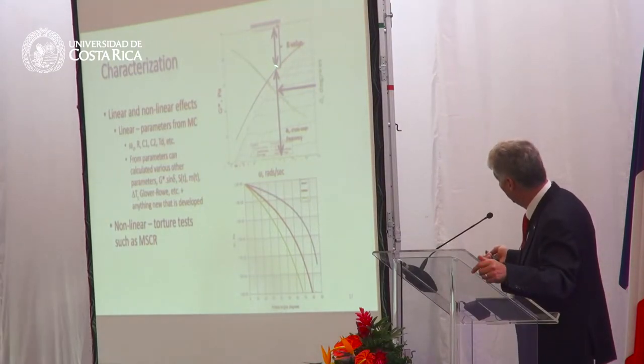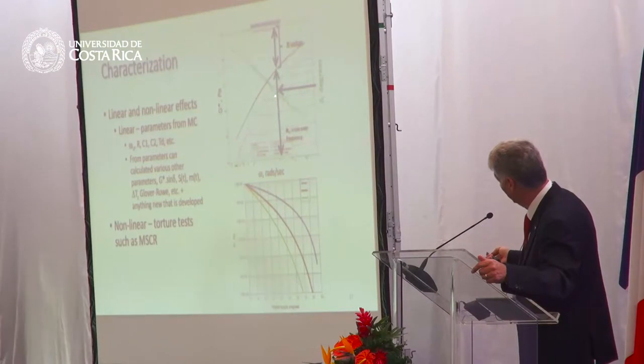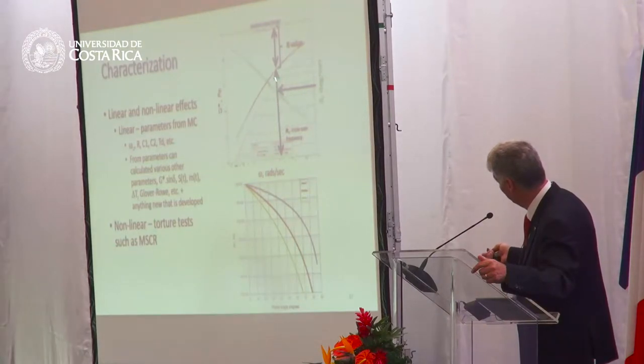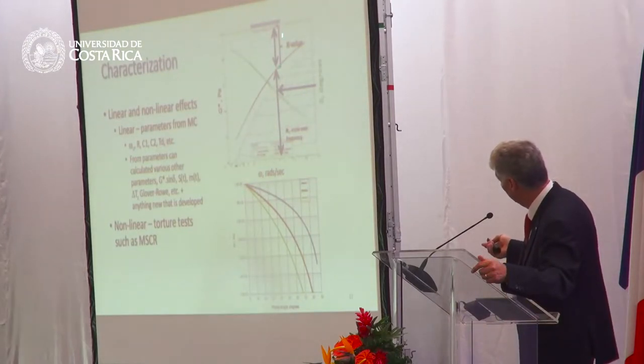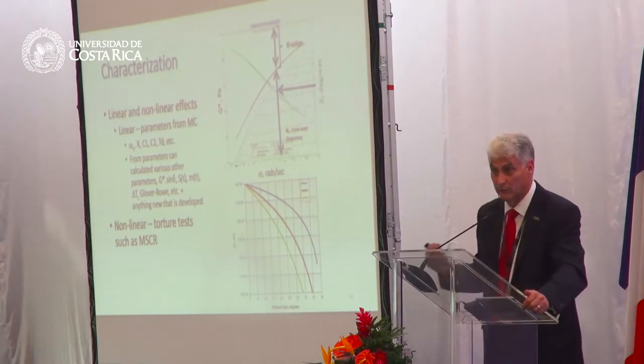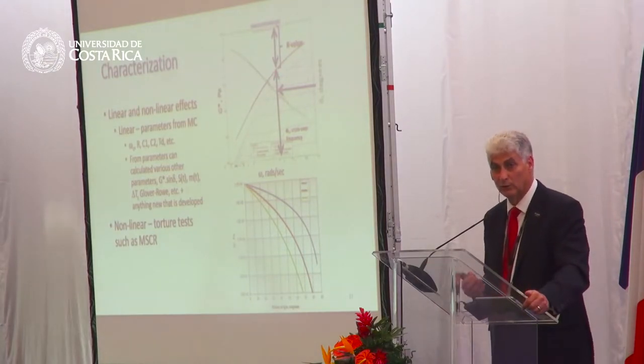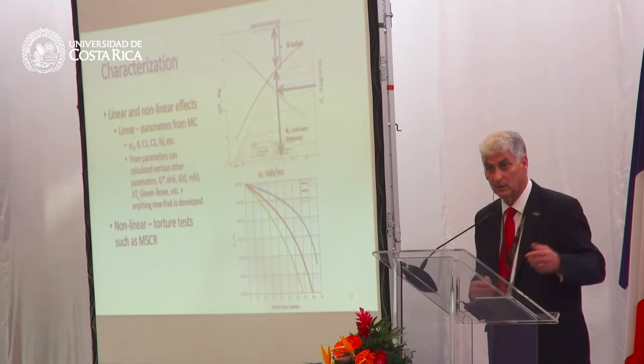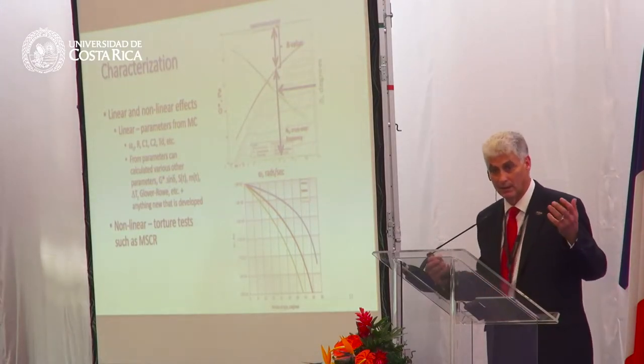There's a couple of values here I've shown. This value is from a point where the phase angle equals 45 degrees. This characteristic here is what we call the R value, the rheological index. That rheological index relates to delta Tc. It relates to the Glover-Rowe index.